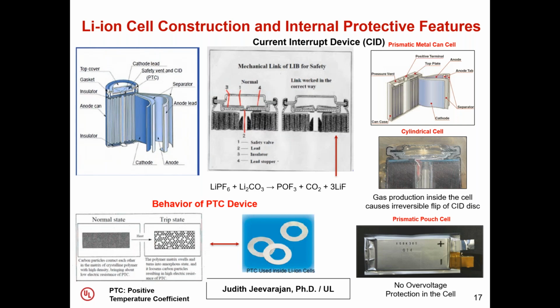At this point, it's an irreversible action where the mechanical touching of the two discs is disrupted. And when this happens, you have a dead cell and you can no longer charge or discharge the cell, but we call it a fail-safe mode because the cell has failed in a safe manner. The same type of device is also found in a prismatic metal can cell. When we look at a prismatic pouch format cell, that type of device is not placed in the cell.